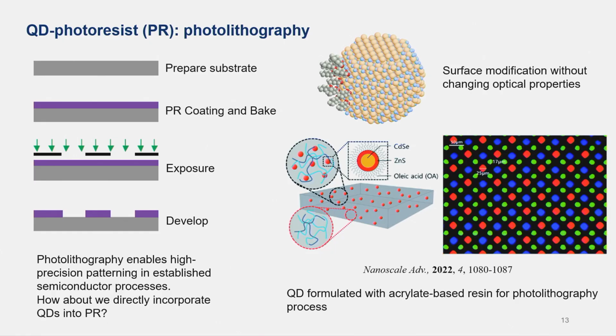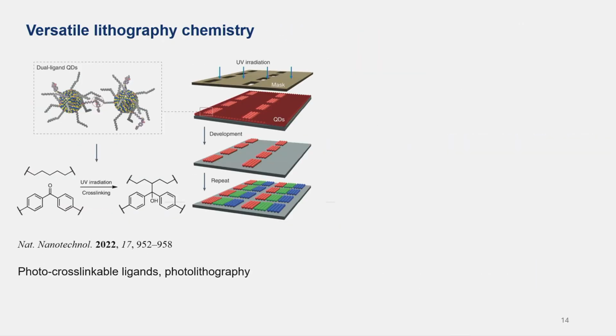So there are definitely a lot of strategies to do it. If you don't want to do a ligand change, then you can formulate your photoresist inks, mix them, and make a stable photoresist ink. Or if you want to play with the organic reactions, you can ligand-change the surface into, for example, photo cross-linking ligands, which polymerize under specific conditions, for example, UV light.